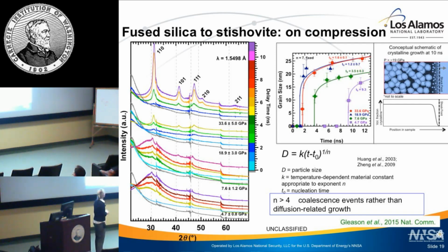And so n greater than 4 is associated with something like coalescence events or aggregation of nanocrystalline particles. Okay? So the grain size here is only something like 20, 25 nanometers. So very small particles of SiO2 are coalescing or aggregating, okay? And that's how this transition is taking place. So here's sort of a cartoon of what's happening behind the shock front. We start out with very small grains, and then very rapidly, say even just in a few nanoseconds, we're immediately blossoming into these slightly larger nanometer-sized grains.